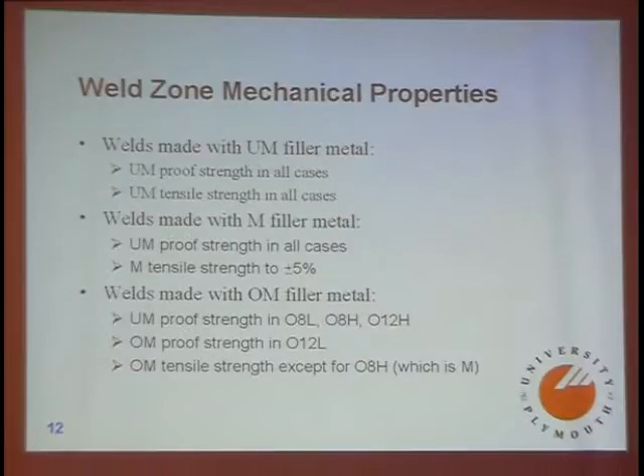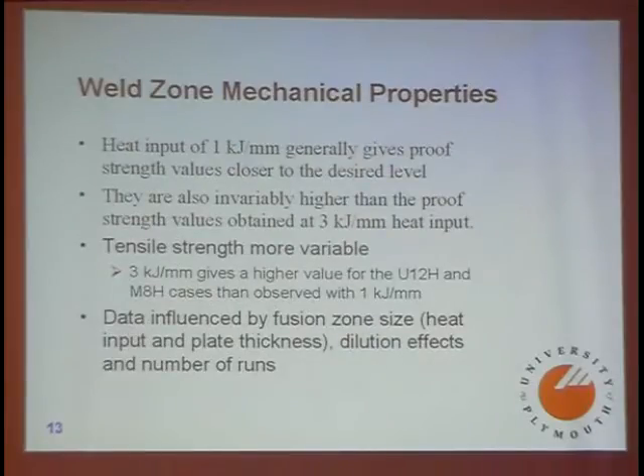So as you steadily increase the strength of filler metal, it becomes more difficult to actually predict what the weld property is going to be, at least in this high strength steel. And another set of generalizations you can draw out is that the lower heat input generally gives proof strength values close to the desired level. They're also invariably higher than the proof strength values obtained at 3 kilojoules, which is a reasonable conclusion. You would expect that. But the tensile strength is more variable. And there are certain cases where the higher heat input gives you a higher tensile strength than you get with 1 kilojoule per millimeter. And so the supposition is your data is influenced by fusion zone size, which is a function of heat input and plate thickness, dilution effects, and the number of runs, and it is going to be quite complex to actually predict what you do get, except the undermatch does seem to work fairly well.